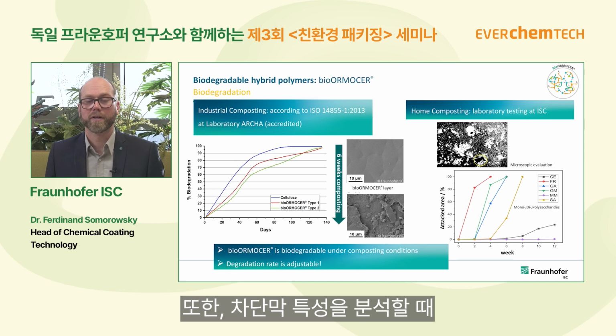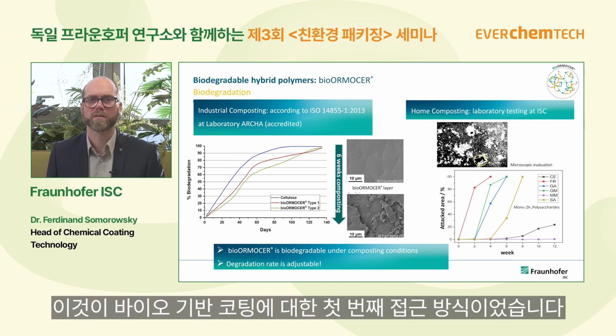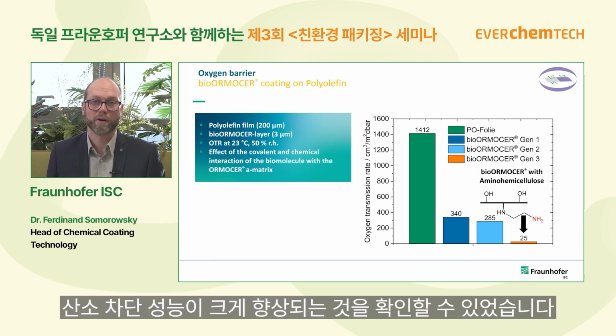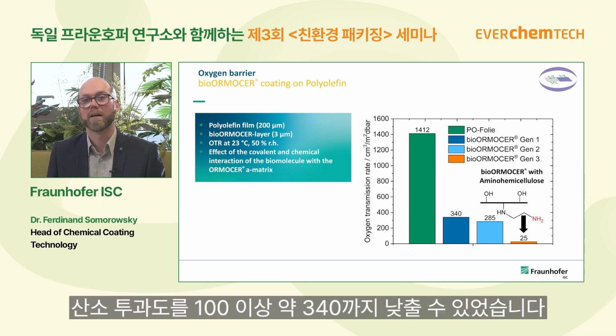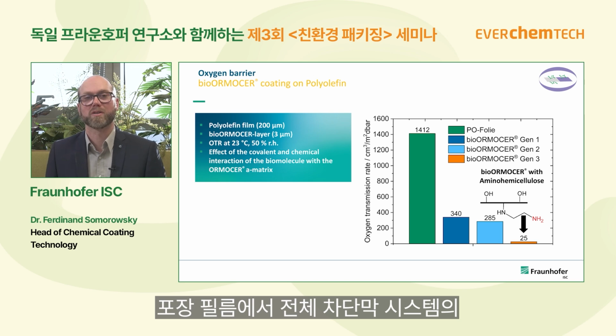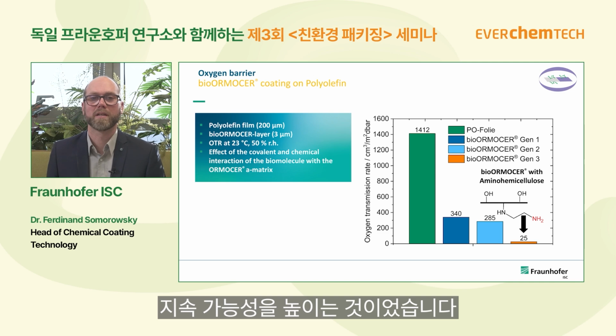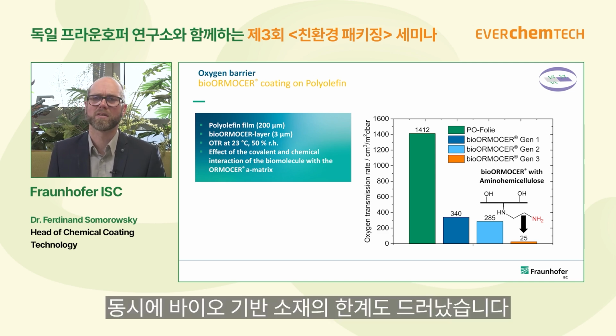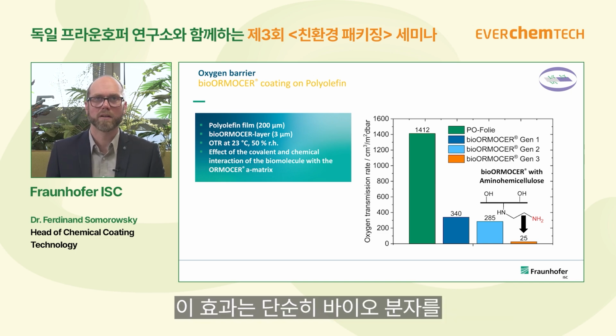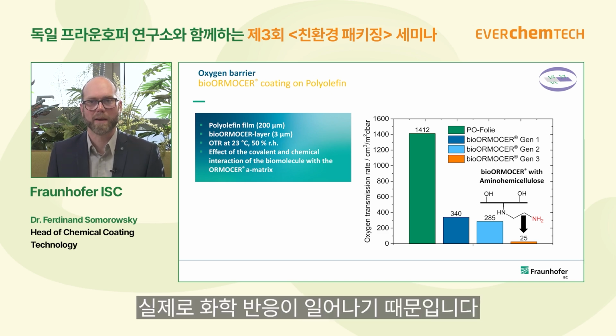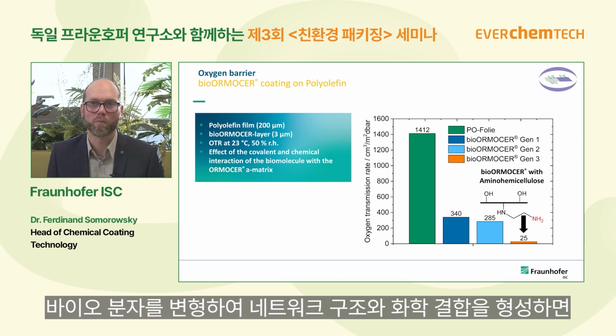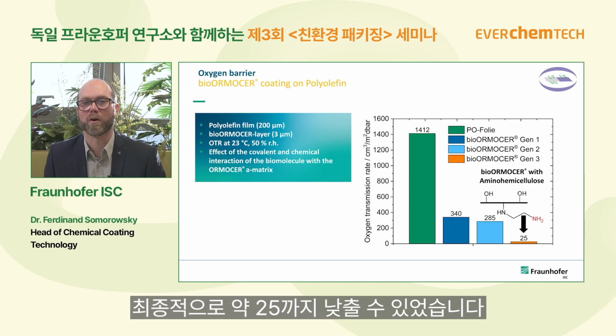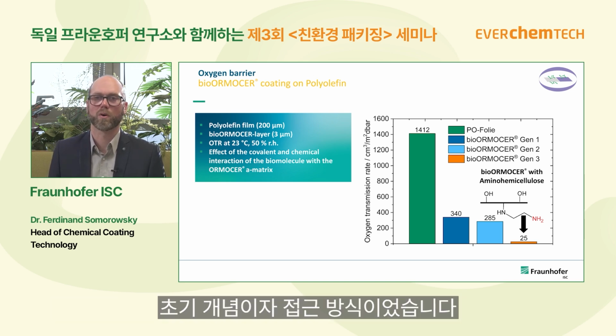When you look at the barrier, and also that was the first approach for the bio-Ormocer, we can improve the oxygen barrier of polymer film, for example, quite a lot, from more than 1400 to around 340. The initial idea for the bio-Ormocer was the application on packaging films to improve the sustainability of the whole barrier stack. That is quite high, and here we saw also the problem of the bio-Ormocer. It's not only a mixing in of the biomolecules in the Ormocer matrix, it's really a chemical reaction. And when we modify the biomolecules and achieve a chemical bond between the biomolecules and the network structure, we can improve the barrier quite a lot and achieve values of around 25. So that was the initial thoughts, initial approach for the bio-Ormocer.